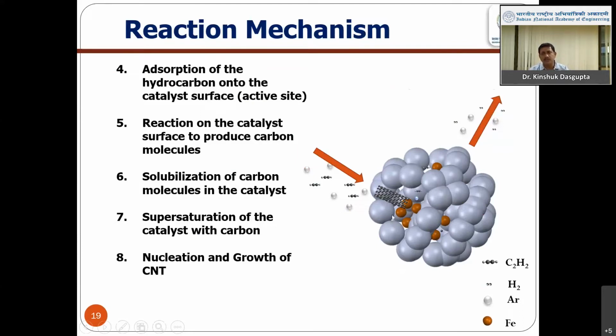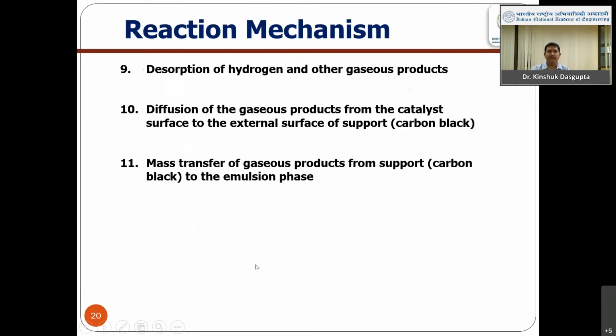They go on dissolving, and once they reach saturation and then supersaturation, the carbon would like to come out in a tubular form. At that particular condition, the tubular structure is the thermodynamically stable structure, so it will come out as a tubular form, and that is called nucleation, and then the growth of the carbon nanotube. Whatever gaseous products, that is hydrogen and others, follow the reverse path. Initially they come out through the pores, then from the pores to the external surface, then to the bulk, and finally they come out.